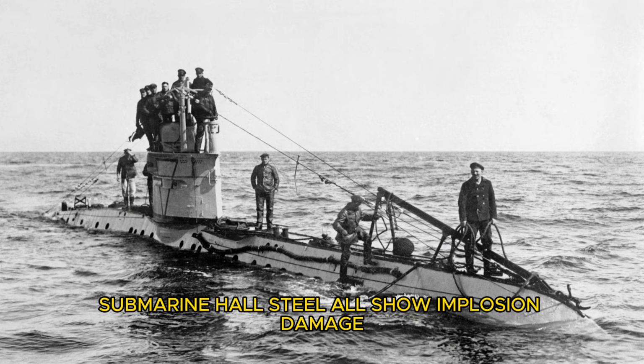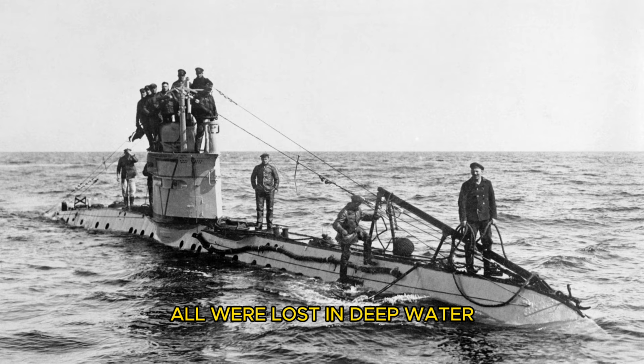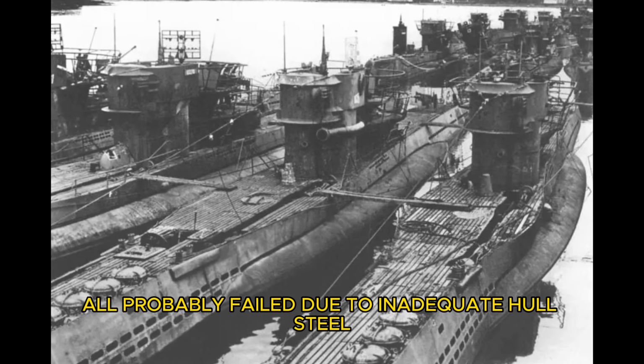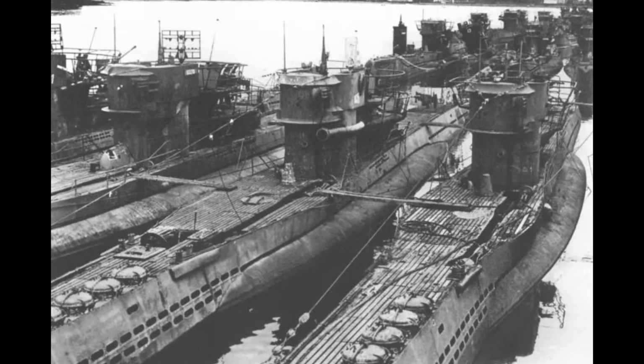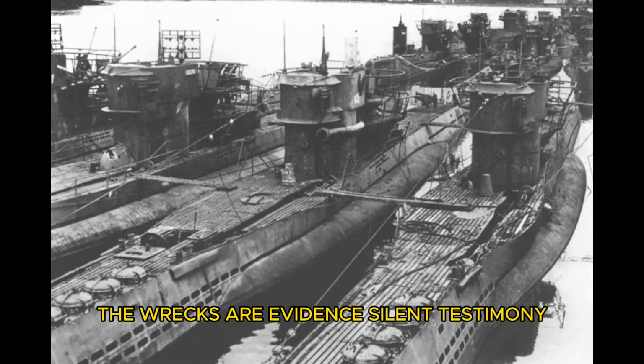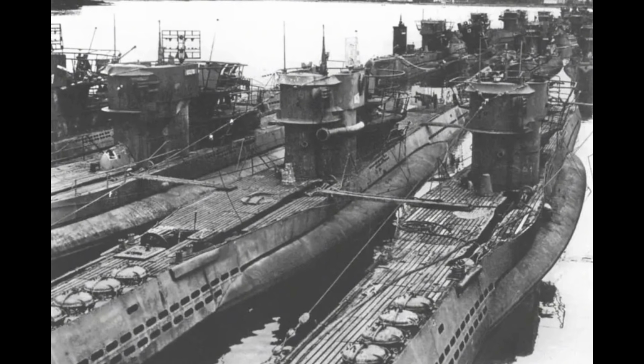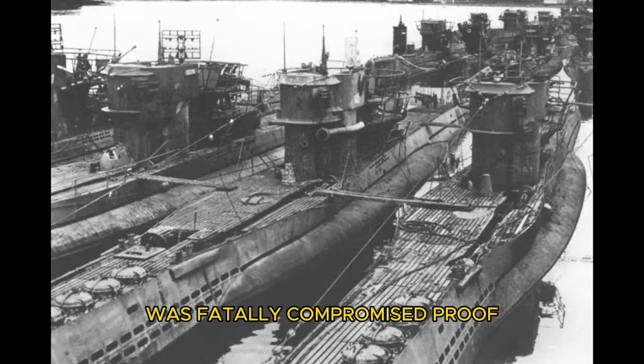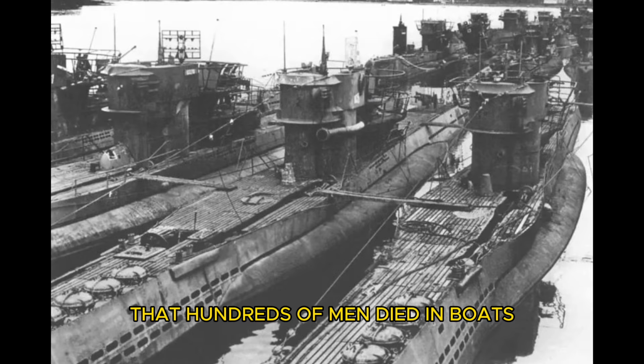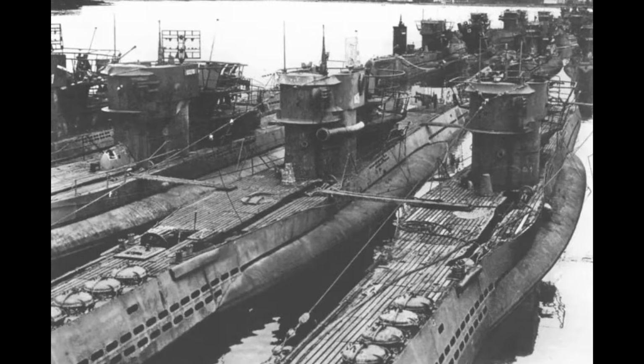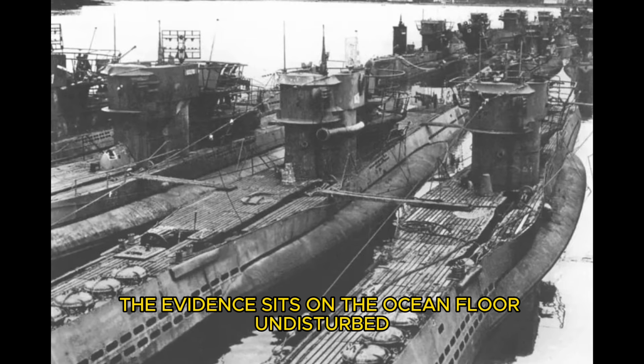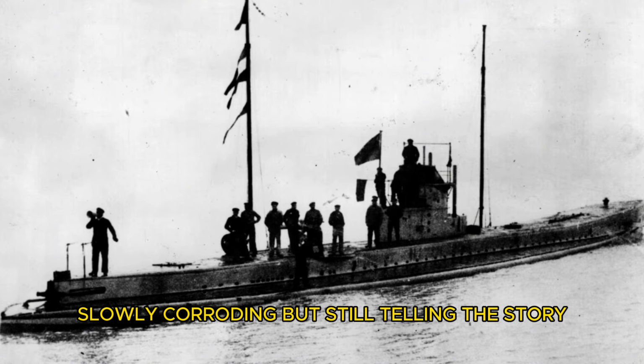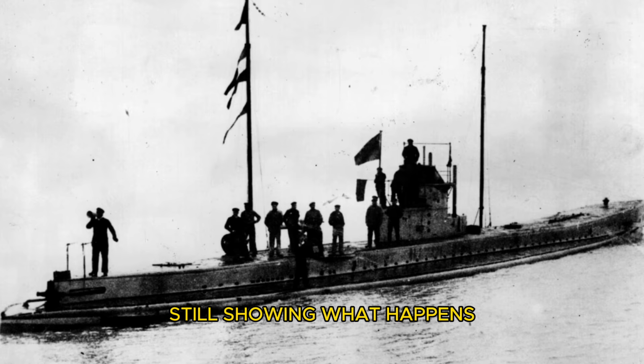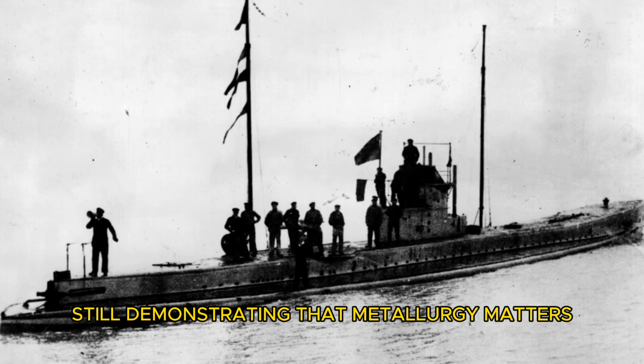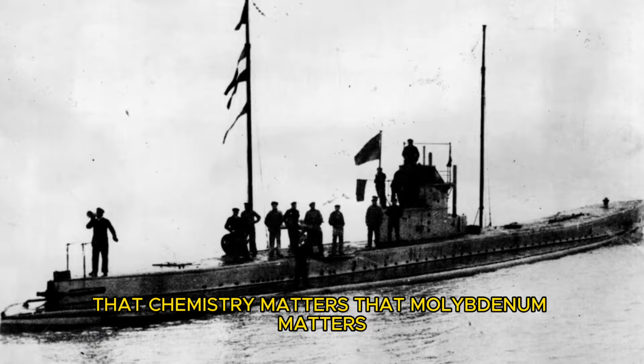Submarine hull steel all show implosion damage. All were lost in deep water. All probably failed due to inadequate hull steel rather than direct depth charge hits. The wrecks are evidence, silent testimony, proof that the analysis was correct, proof that German submarine steel was fatally compromised, proof that hundreds of men died in boats that should never have been sent to sea. The evidence sits on the ocean floor, undisturbed, slowly corroding, but still telling the story, still showing what happens when you compromise materials in pressure vessels, still demonstrating that metallurgy matters, that chemistry matters, that molybdenum matters.